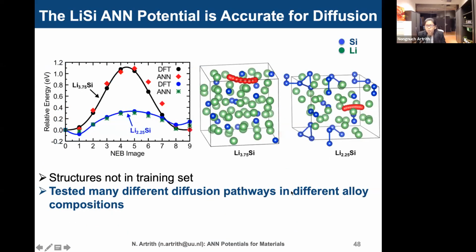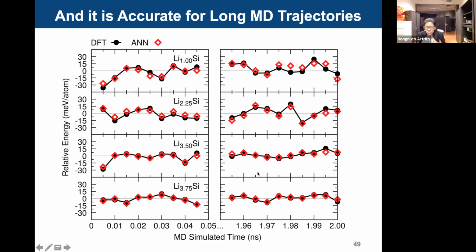And then we also validate our neural potentials for lithium diffusion paths. As you can see here, the agreement between neural potentials and DFT is excellent in many different channels and also different lithium concentrations in the structures. And not only that, we also check how good the forces are so that we can use them in long MD simulations. In this case, I demonstrate only 2 nanoseconds, like you can see here.